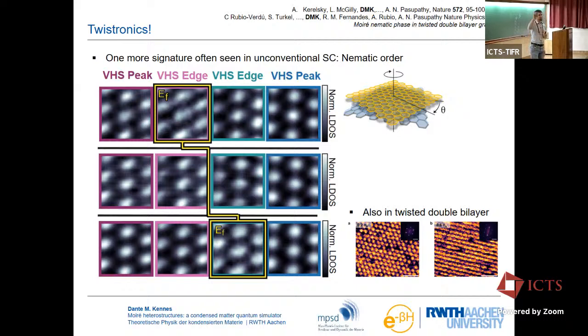If you have this magic angle structure where the bandwidth rapidly plummets down, little angle variations that you always have will have huge effects on your system. So your bandwidth will be disordered rather strongly. If you have a nice, smooth, continuous function, then you can maybe live with these angle variations. And because that's easier to control experimentally, one can do this experiment, and these results are shown here.